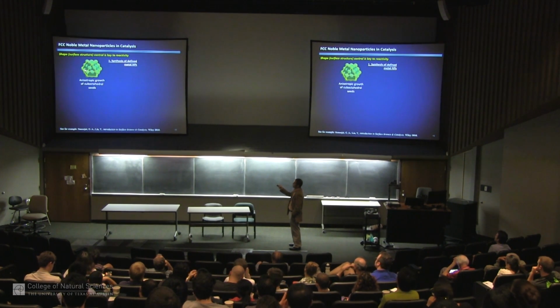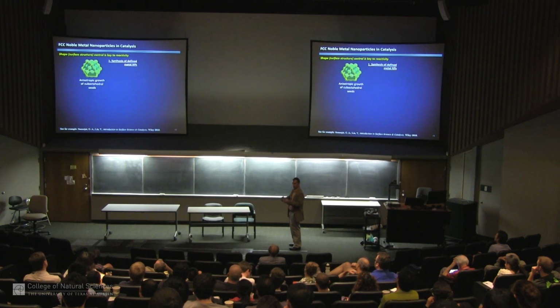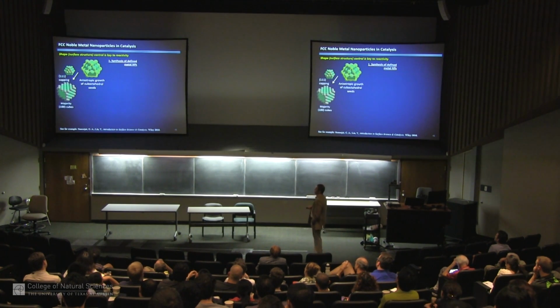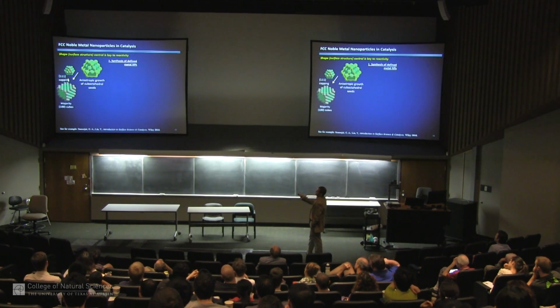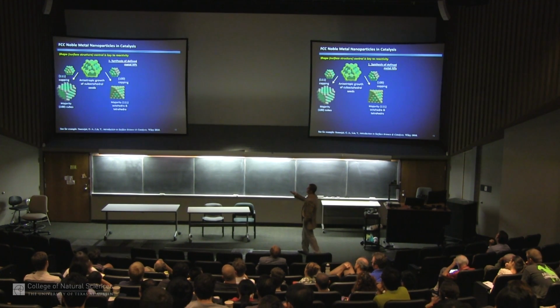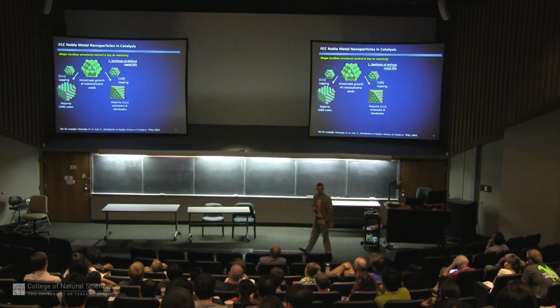And remember I said you've got to control the surface chemistry because a square face is less densely packed than a triangular face. This is like packing pool balls in a pool triangle before you start a game. This is a less dense arrangement, and so the binding chemistry is different on these faces. So if we can control the chemistry kinetically, and for example only grow on triangular faces, you should end up with cubes that have more selective chemistry on their surfaces. And conversely, if you grow on square faces, you should get octahedra and tetrahedra, which are equally selective.